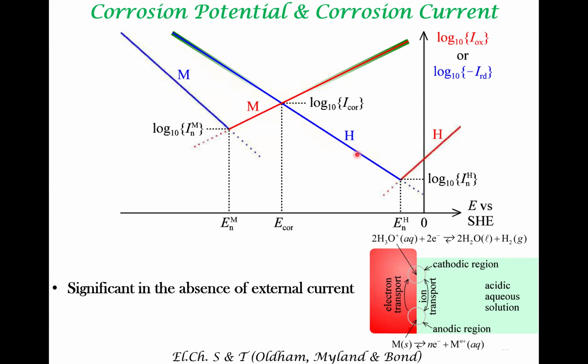experimental measurements involving a 2-electrode setup or also a 3-electrode setup. I mean, rather a 3-electrode setup, because we want to get a measure of the potential of the corroding sample. What I meant by a 2-electrode setup is that because we have an anodic region and a cathodic region here, which cannot be separated, we separate these two regions via an explicit 2 electrodes. And to get the potential of the corroding sample, we use the third electrode, which is the reference electrode. The second important aspect of corrosion is that at E corrosion, the rate of generation here matches the rate of consumption in this reaction.